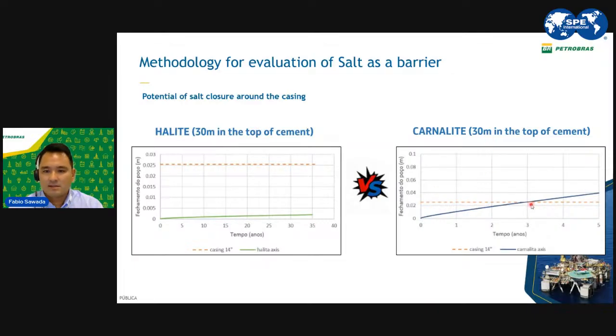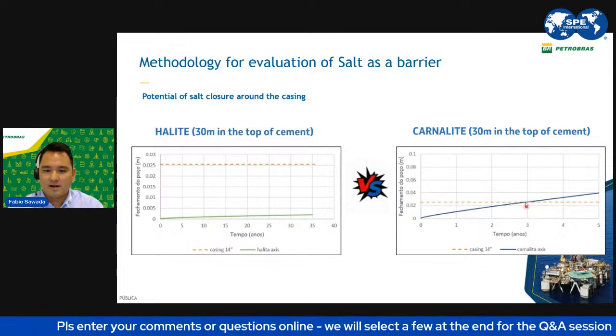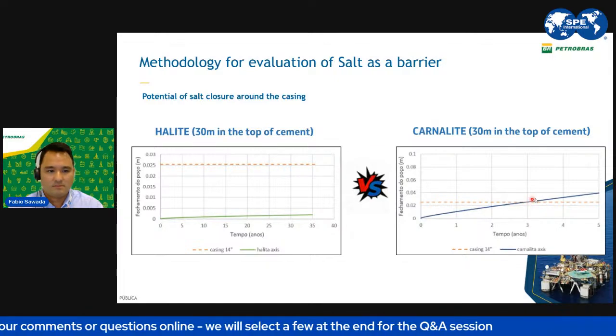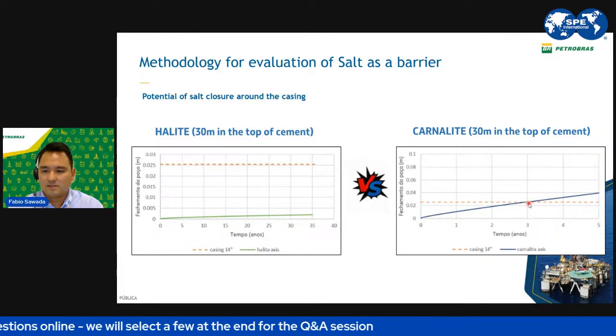So when we see carnallite in the same conditions of temperature, the same depth, and the same overburden, we can see that the carnallite would form a barrier and touch the casing in a period of 3 years. So it's really very fast and has a very high closure distance here compared to the halite.